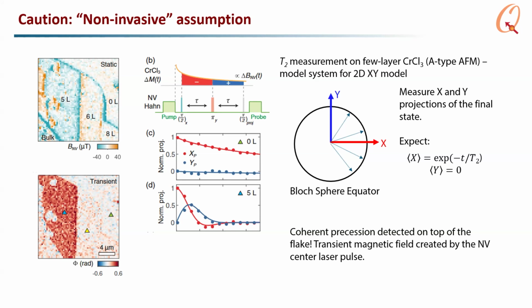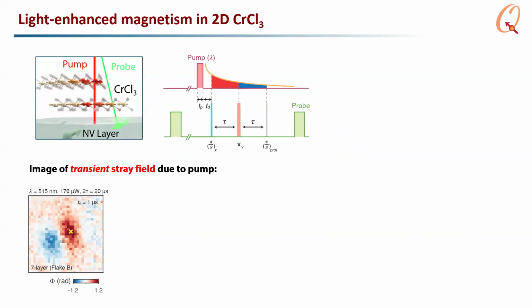So there's some transient magnetic field that's synchronized to the laser pulse. The first laser pulse that I used to initialize the NV center spin actually creates a transient magnetic field. We got sidetracked by this, spent too much time studying it, and ended up writing a paper. So instead of using the green laser pulse, we put in another laser color where we can vary the wavelength,